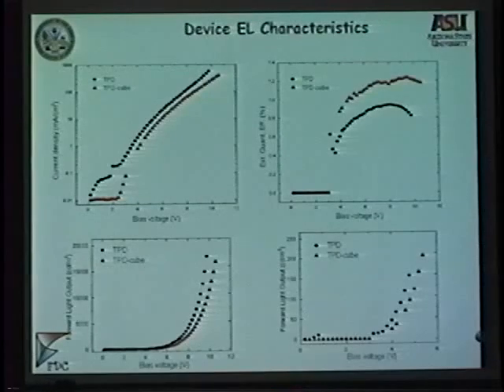In order to form a high number of excitons, you always have to balance the electrons and the holes, because after all, light is the exciton relaxation. So this is what we need to do, and by doing so, we increase the efficiency of the device from the molecular material all the way up to the cube here reasonably well.